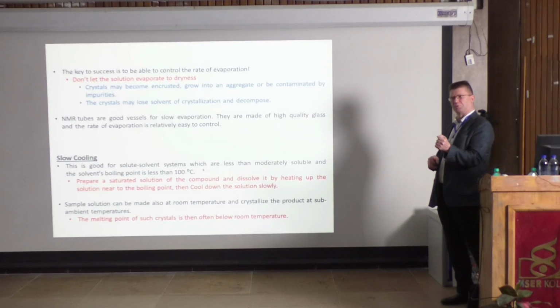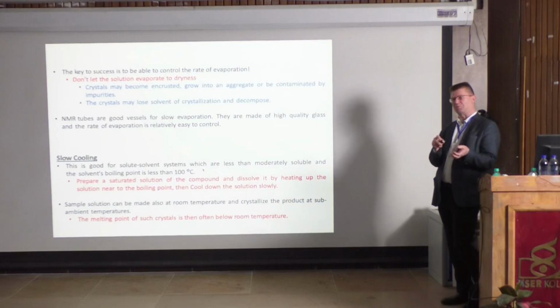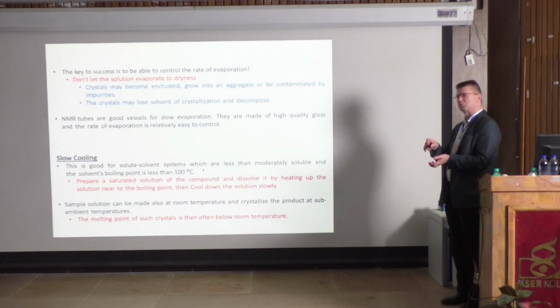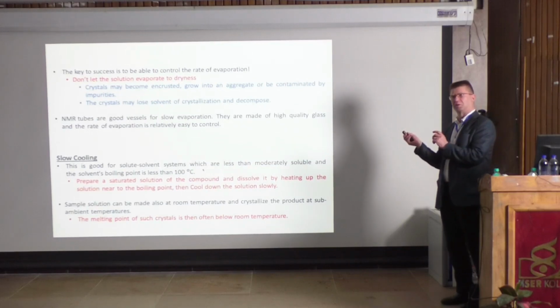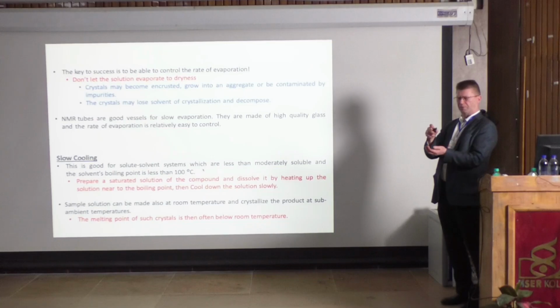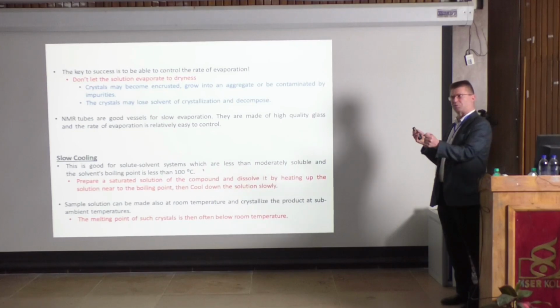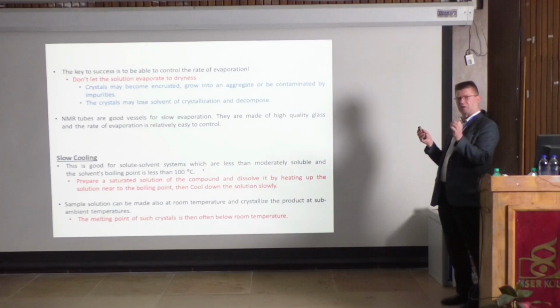So what you have to do, you have to be able to separate the crystals which are formed at low temperature, at low temperature, to remove the solvent. And one thing is, of course, that if the crystals are on the bottom of this thing, you just quickly remove the cold solvent and then keep the crystals in there. They might survive when they are dry, because they are soluble in the solvent, not in the air.